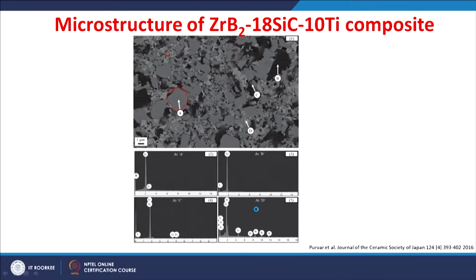So, the zirconium diboride grains and the silicon carbide particles are distributed, and then we can see the EDS analysis of these particular phases. This A phase is zirconium diboride, you can see significantly the zirconium and boron. And you can see this black or dark phase which is rich with silicon, so this is silicon carbide.